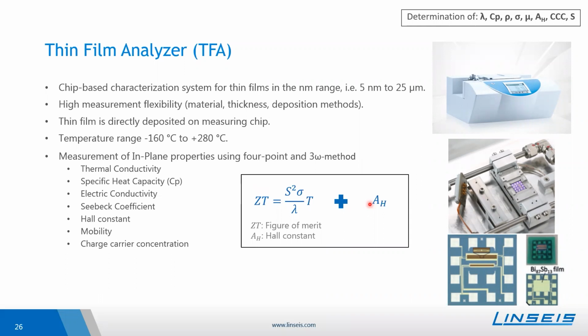The measurement method uses a chip where these pads are all used for the measurement. So it's an integrated characterization system with this chip where you directly evaporate the thin film onto it. It's especially for very thin films in the low nanometer to about 25 micrometer range.